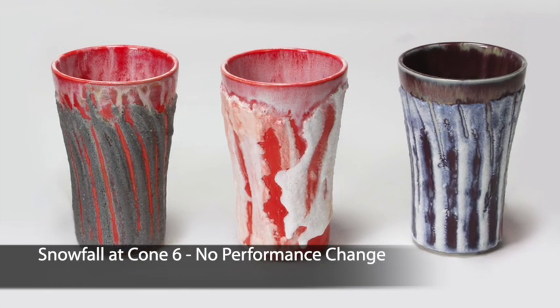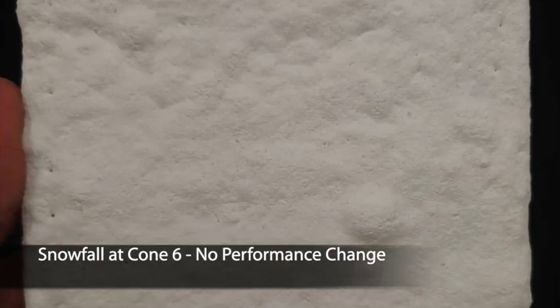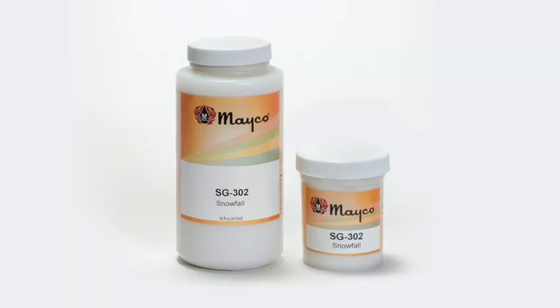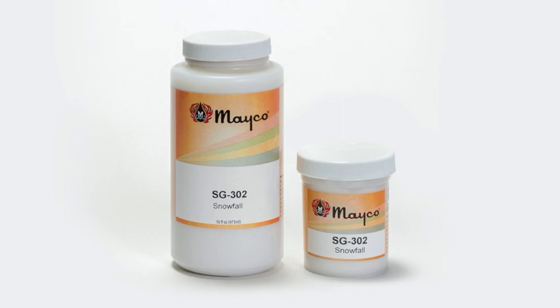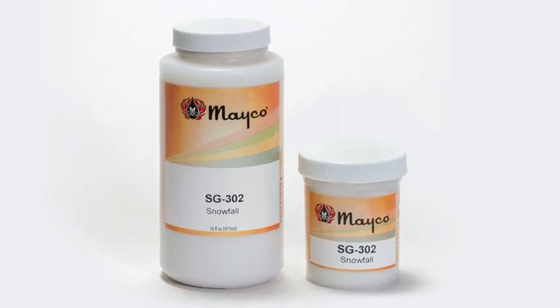Snowfall has a wide firing range. The previous images were cone 06. Now you can see that Snowfall performs the same even at cone 6. When applying Snowfall, apply 2 or more coats over unfired glazes at shelf cone 04. You can apply it to bisque, greenware, or clay.